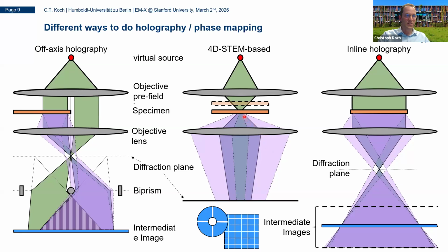So the idea is you have a focused probe, or nearly focused, or at least with a small size that you scan across the sample. You might also defocus it if you really want to limit beam damage. For example, in life science, people apply defocused ptychography a lot, but also in materials science, this may have an advantage when you want to minimize the damage due to dose. And then you scan this beam across the sample and you collect the diffraction pattern at each probe position.